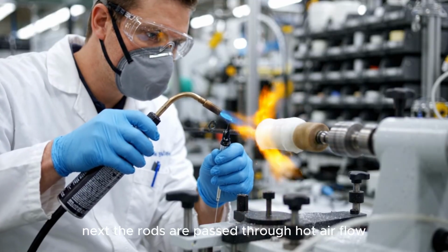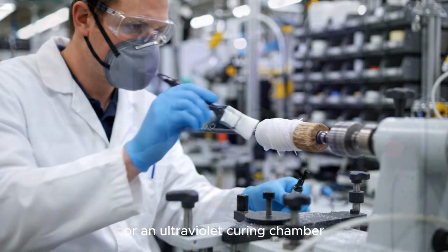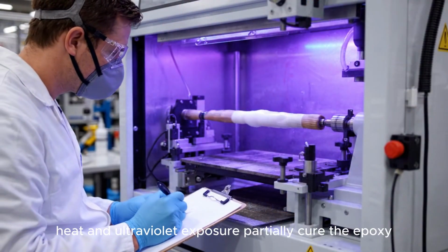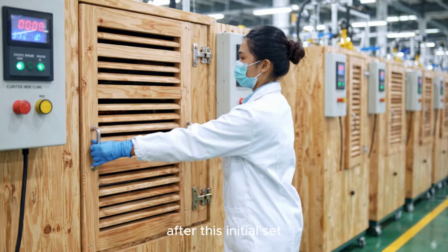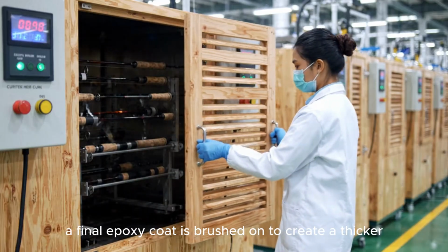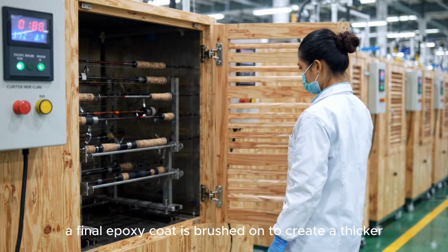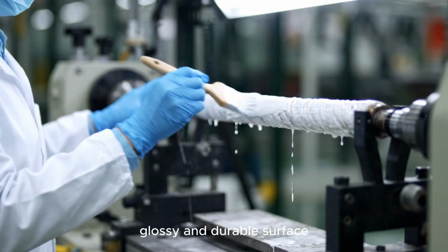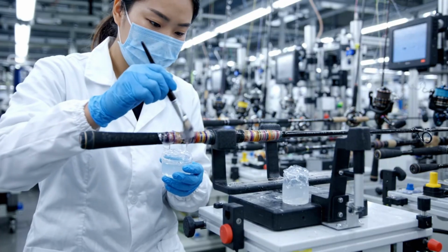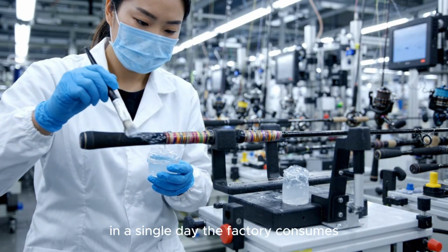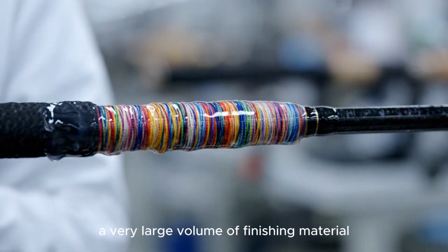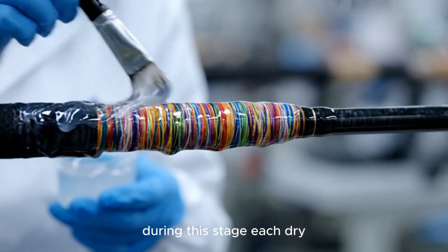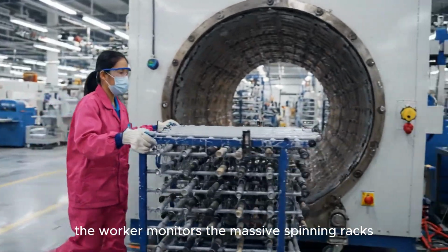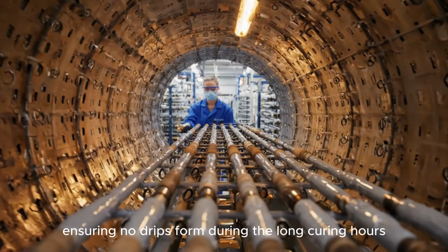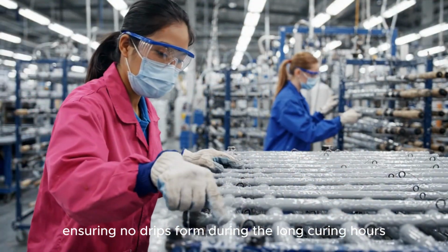Next, the rods are passed through hot airflow or an ultraviolet curing chamber. Heat and ultraviolet exposure partially cure the epoxy. After this initial set, a final epoxy coat is brushed on to create a thicker, glossy, and durable surface. In a single day, the factory consumes a very large volume of finishing material during this stage. During drying, the worker monitors the massive spinning racks, ensuring no drips form during the long curing hours.